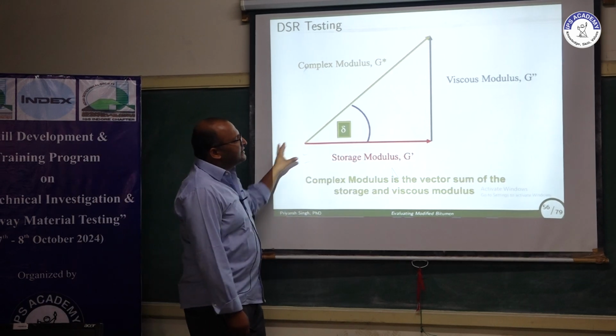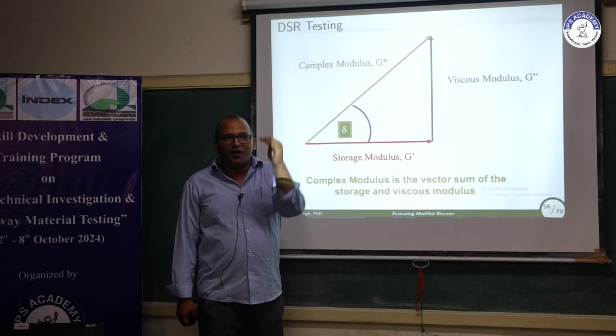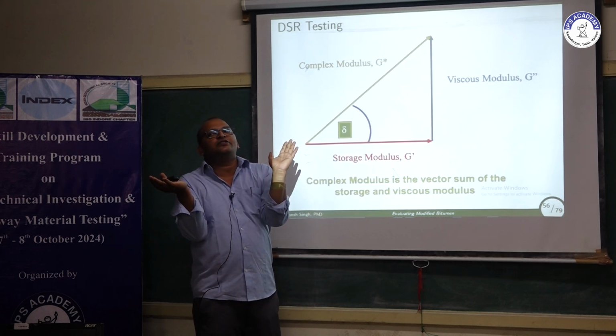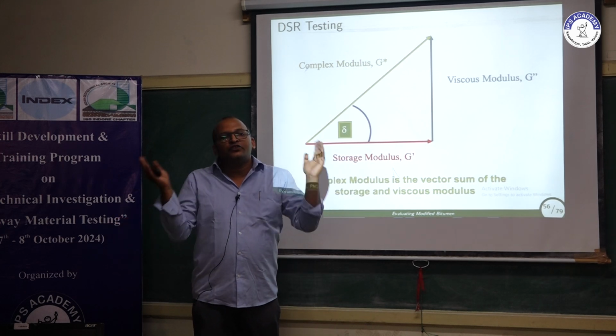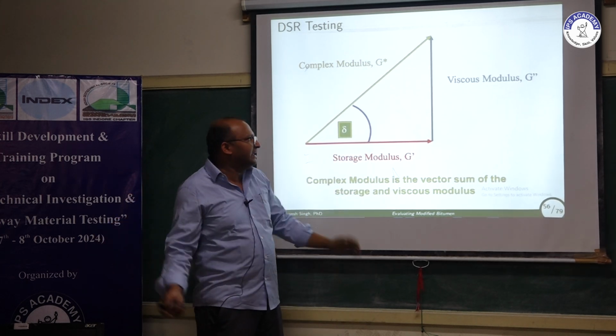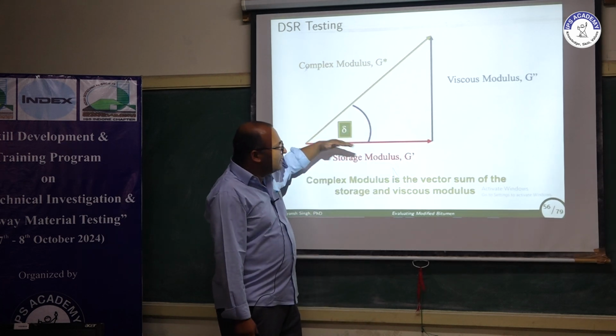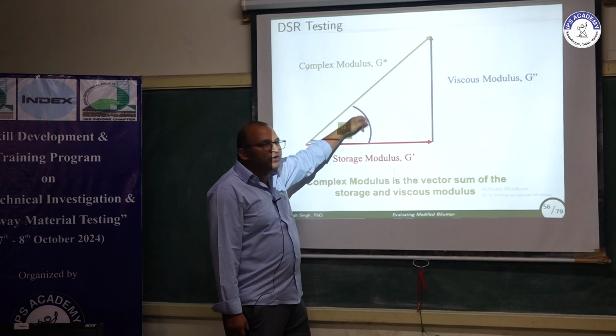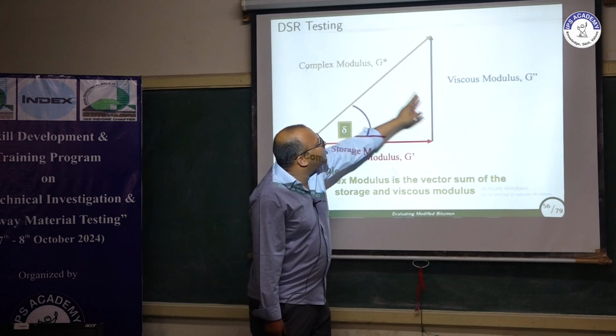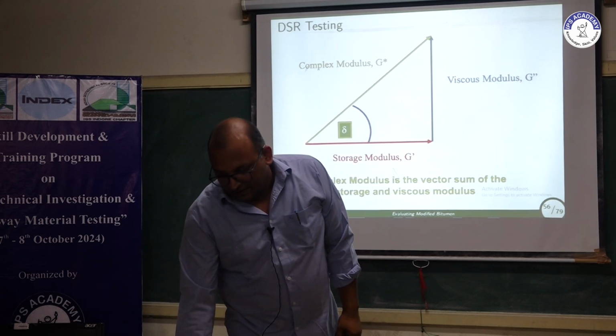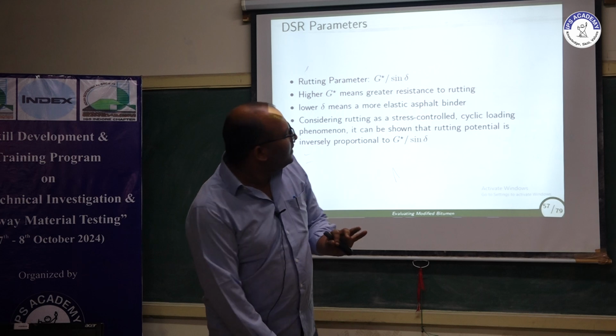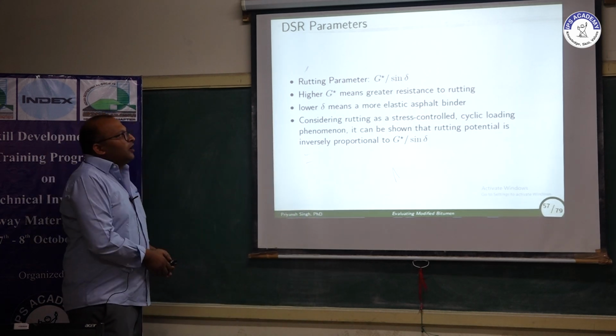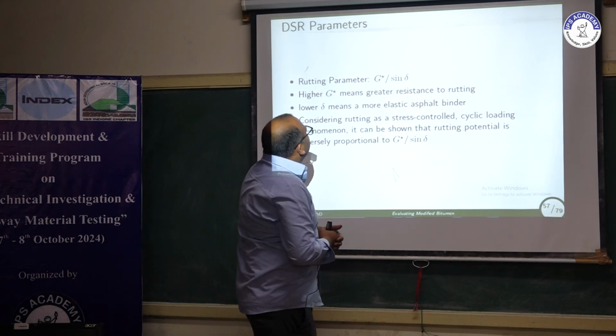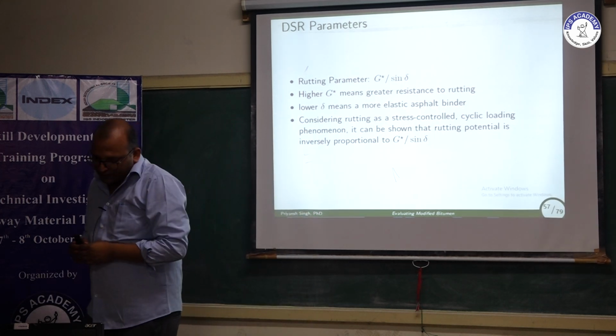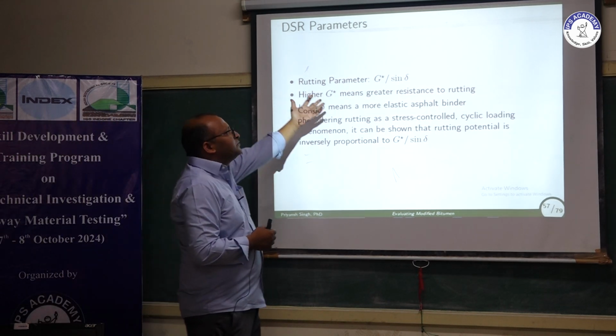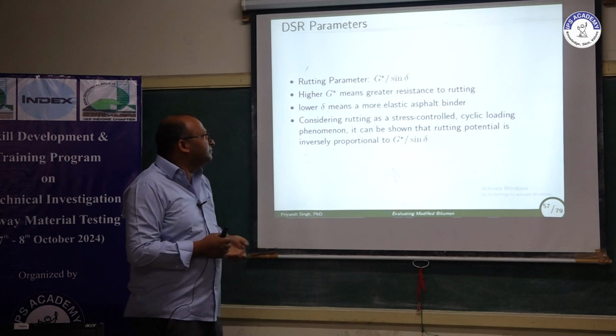Here this complex modulus we signify as a complex number. Now in this complex number we have two components. As I told you, a viscoelastic material will show viscous and elastic behavior, so we will try to separate out this viscous and elastic behavior. There will be a viscous modulus and a storage or elastic modulus, and this delta is your phase angle that you have calculated. The modulus of these two will be your complex modulus. This complex modulus is a very important parameter which will signify all the properties. Once you have estimated your complex modulus and phase angle, you can calculate a rutting parameter as specified by FHWA, which is the complex modulus divided by sine delta, or sine phase angle.